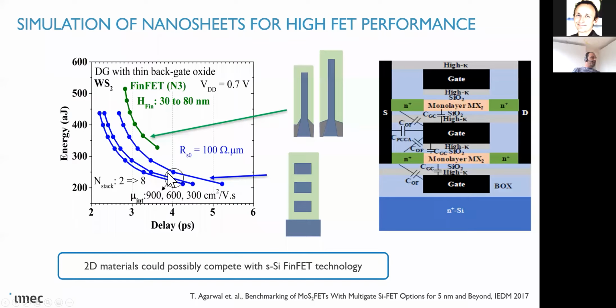And then the difference that you see between this bullet and these bullets is the fact that in this assumption, we assume that we can have 300 centimeters squared per volt second mobility in the tungsten disulfide, then 600 and 900. We do not reach these values today, but at least it shows that even with a relatively modest mobility, we could be competitive with these numbers.